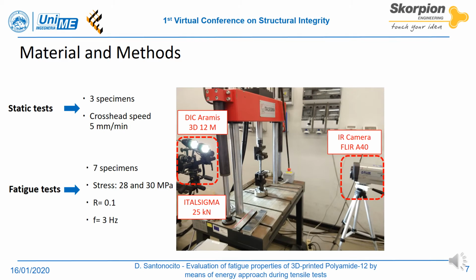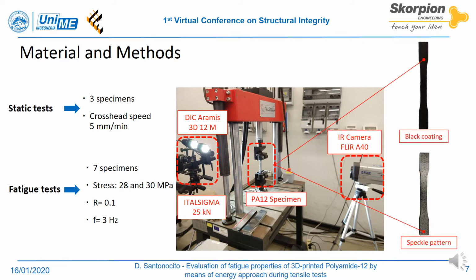The static tests were performed with a servo-hydraulic load machine Ital Sigma 25 kN with a cross-head rate equal to 5 mm per minute at constant temperature and relative humidity. The tensile tests were carried out on 3 specimens, and an infrared camera FLIR A40 with a sample rate of 1 image per second was adopted to monitor the specimen's surface temperature. Longitudinal displacements of the specimens were assessed by means of a digital image correlation system. The specimen surface was coated with a high emissivity black paint on one side, while with a speckle pattern on the other side. A series of fatigue tests at constant amplitude was performed on 7 specimens of the same geometry as the previous ones, with a stress ratio of 0.1 and a test frequency of 3 Hz.